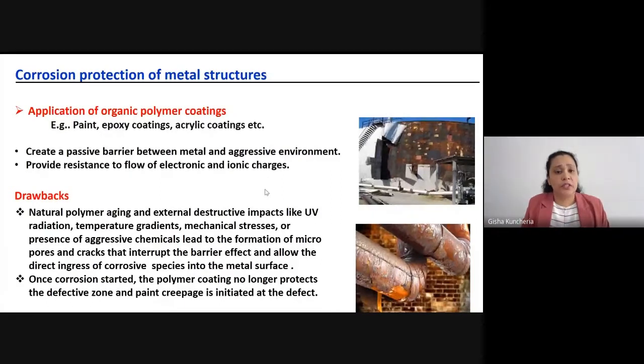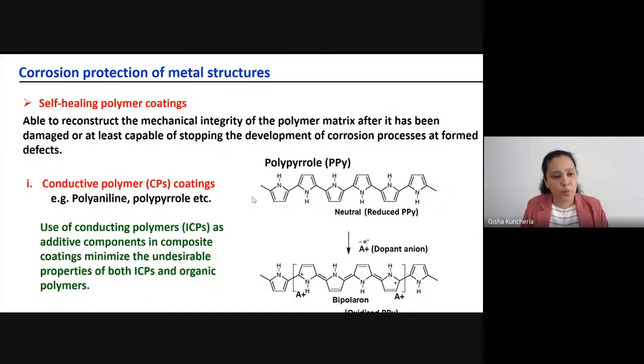So how can we solve this issue? The existing solution is self-healing polymer coatings. What is self-healing? Self-healing means when a crack or any defect is formed in a polymer, the polymer itself will seal it, or reconstruct the mechanical integrity of the polymer. Or when corrosion starts on the metal surface, the polymer coating provides some technique to stop the corrosion, or reduce or diminish the corrosion process. Such types of coatings are called self-healing polymer coatings.